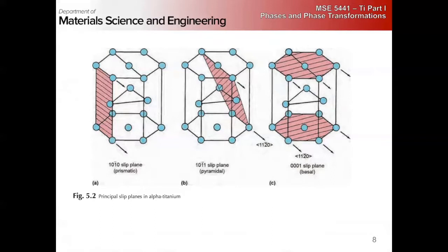This is going to be a lot harder, especially at room temperature, to activate. What about temperature dependence of the slips? You have a non-close-packed slip direction, a larger burgers vector. No, no, no, this is just showing the direction. That's not the actual slip direction. The slip direction is 11 bar 23.